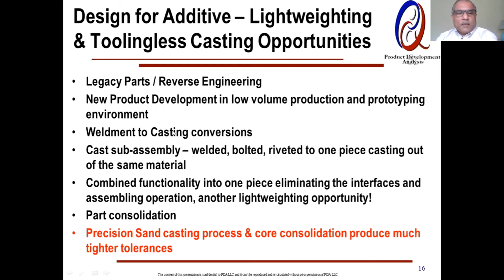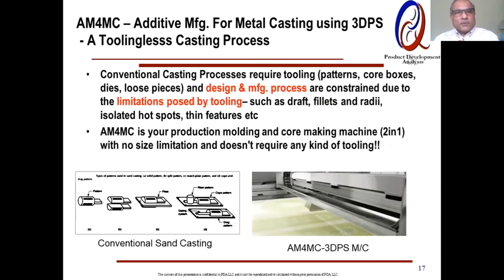So another thing we have seen is with the additive, especially 3D printed sand, that these are digitally made, so there is no tooling wear and tear related. So every time you make a mold, it's dimensionally accurate with the precision of maybe 0.5 millimeter. And so I call it precision sand casting, because it really helps you further narrow down your tolerances, make the walls thinner, and get the light weighting. I'm sure most of you are aware of the process, so I'll just zip through. This is making 2-in-1, I call it, making mold and core out of the same machine without any tooling.